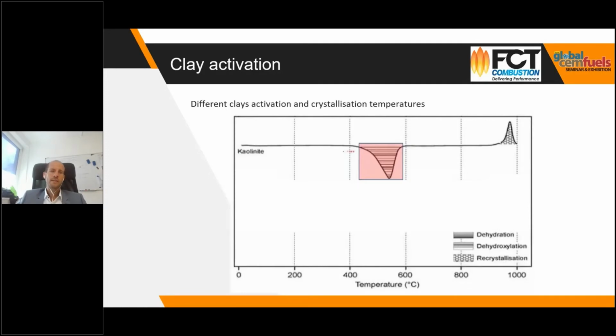Basically, we can see this better in the next chart here. This is an example of kaolinite. So we can see here in the red box would be the activation temperature. Here on the right side would be the recrystallization temperature, and we can see that kaolinite is being activated between around 450 degrees to 600 degrees, and the recrystallization then starts around 900 degrees. So this is a very easy type of clay to use, because there's a very large difference in temperatures between the activation and the recrystallization of the clay. So you have a very large margin of error.